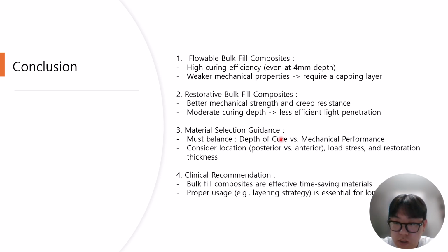Third, material selection should always be a balance between curing efficiency and mechanical performance. We also need to consider the location of the restoration, whether it's in the anterior or posterior region, and the amount of stress it will receive. Finally, the clinical recommendation is simple. Bulk-fill composites are time-saving and effective materials, but for long-term success, it's important to use them properly, especially by applying the correct layering technique based on the material type.